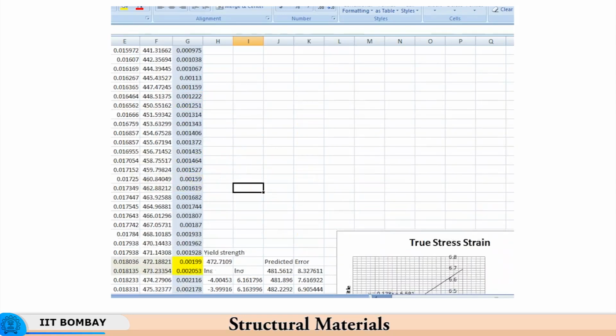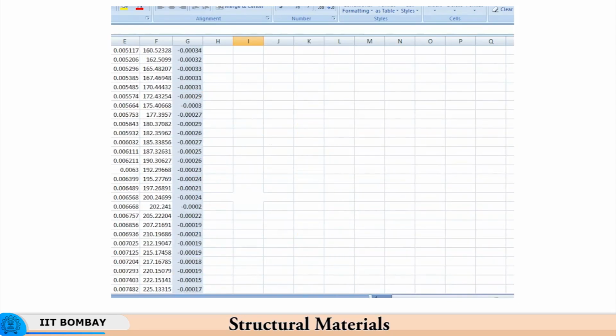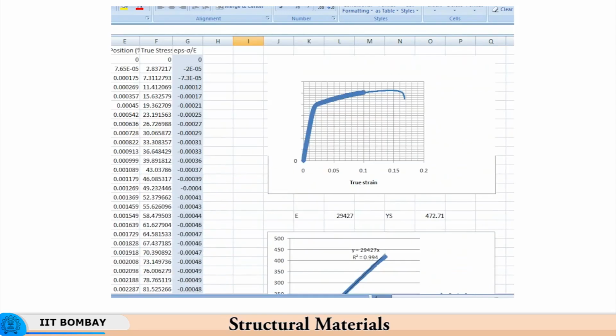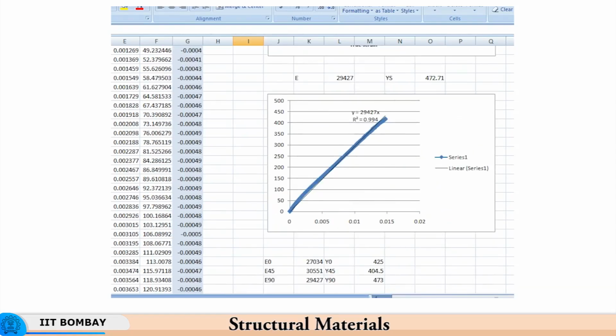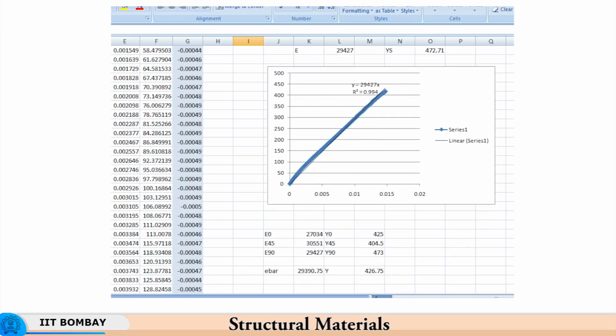Up to this point it is all linear in nature. So, what you do is correlate stress with strain and determine the Young's modulus first. So, the first thing is to determine the Young's modulus. You need to take points such that they lie on a straight line. So, basically when you fit a straight line through this stress strain relationship, R square has to be practically 1, and this is very important.